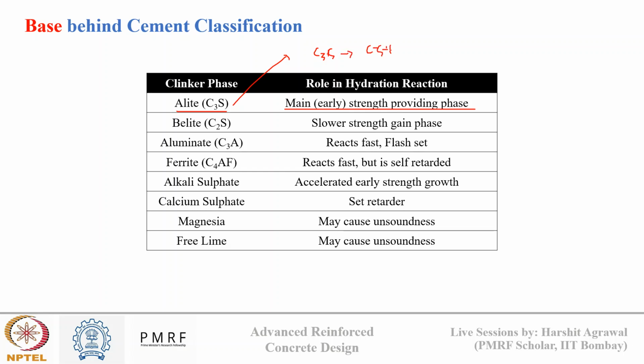And C3S is the main strength providing phase of cement hydration. Okay, and this reacts early also. So that's why we have said main early strength providing phase of cement. Belite, it is slower in reaction. However, it also gives late strength gain in cement hydration. Aluminates, it reacts fast and causes flash setting. Ferrite, it also reacts fast, but it is self-retardant, so that's why we don't talk about ferrite hydration much.